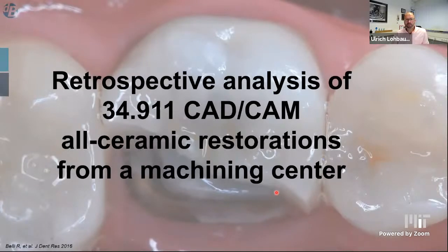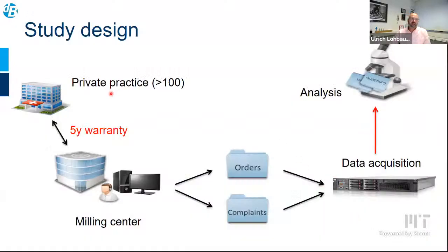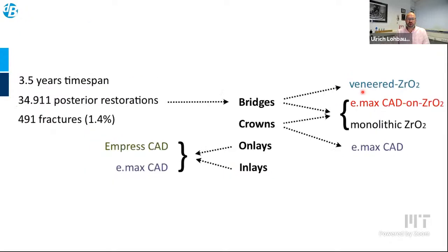To show you a last example, we performed a retrospective analysis of almost 35,000 CAD/CAM all-ceramic restorations, and we retrieved those databases from a milling center, and those milling centers produce hundreds of restorations a day. And we got the database over 3.5 years, and we investigated. So this milling center sends to the private practice, and once there is a failure or a fracture or any complaint, it goes back to the milling center, and we investigated the complaints and analyzed statistically, of course, and then also fractographically in order to see what's going wrong.